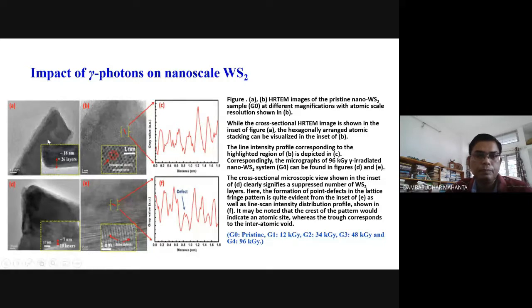So first we have exfoliated these WS2 materials, and then we found that the introduction of defects, and these defects have been analyzed by considering these lattice fringes and plotting gray value against distance. So one can find that in this particular case they are more or less same, but in this case there is a dip inside. So we believe that there could be defects in this case, and these defects, of course, through TEM you cannot say that this is sulfur defect or W defect, but after EDX calculations or elemental detection analysis, you could see that there is a drop in sulfur percentage. So from that we can say that yes, the sample is deficient in sulfur.